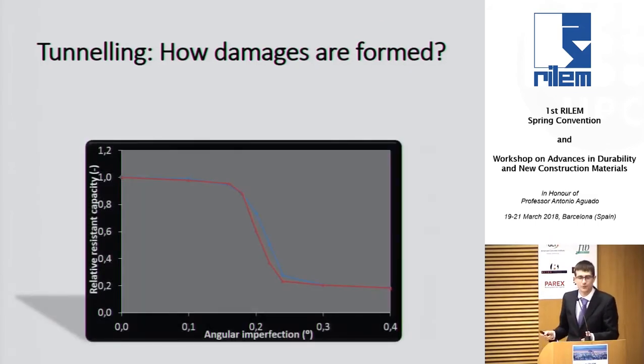And we conducted several finite element simulations, which were complex back then because of the size of the imperfection we were simulating in comparison with the size of the segment. So very small imperfections that we could also measure on site, very big segments in the simulation, right? And the curves that we obtained were something like this. Fortunately, it matched our idea of how it should behave, right?